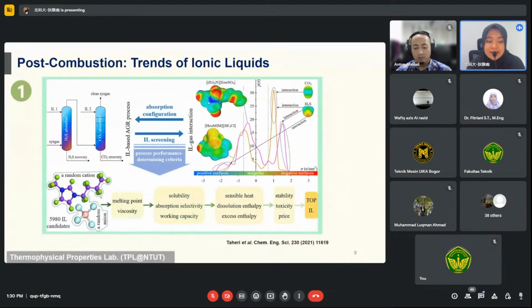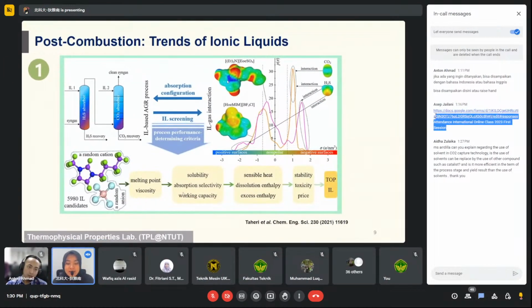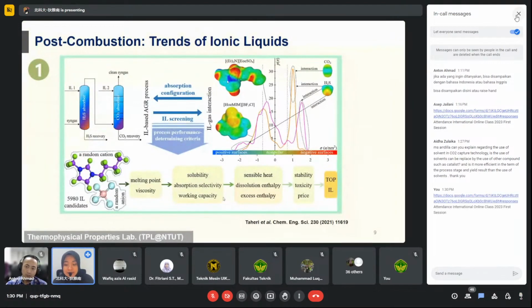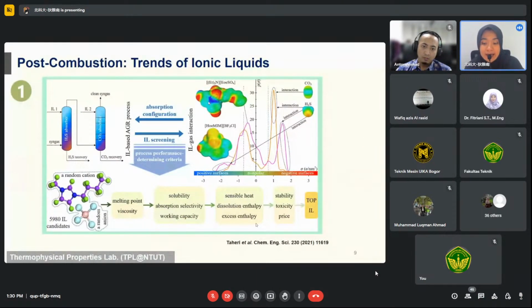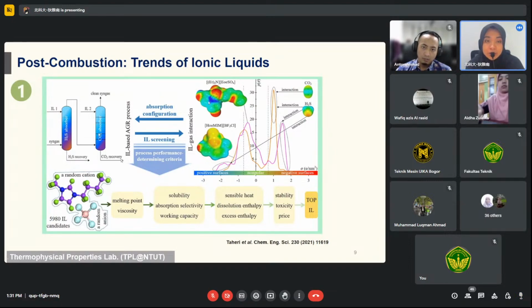So here, you can see that we have around 5,980 ionic liquids. So it's not one ionic liquid, it's thousands. And we try to check the melting point, viscosity, solubility, absorption, selectivity, working capacity. Also, we have sensible heat, dissolution enthalpy, excess enthalpy. And how about the stability? Is it stable or unstable, toxic, the price also? And we can use it as the best candidate to absorb the acid gas, also to absorb the CO2 gas. So later, you will obtain the clean syngas.